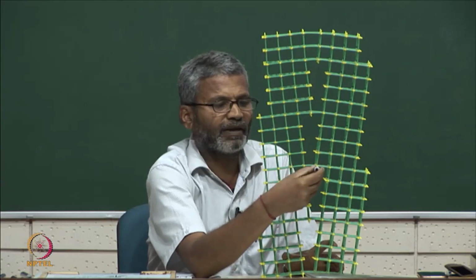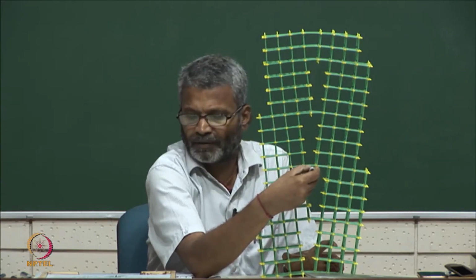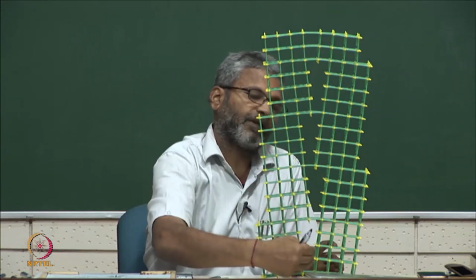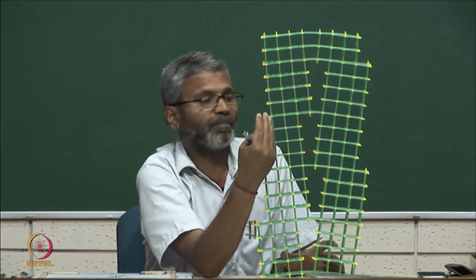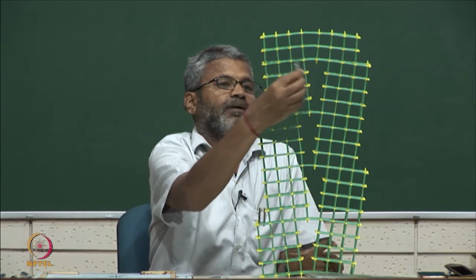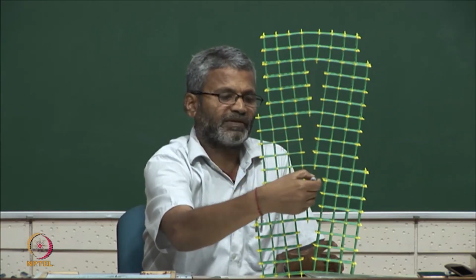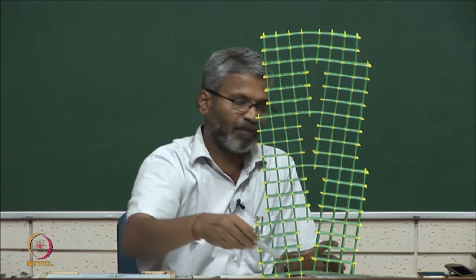So, this is like an extra half plane. This is what I meant when I said that a vertical boundary like this, a symmetric tilt boundary, can be considered as a series of edge dislocations, a set of parallel edge dislocations lying in the boundary plane.